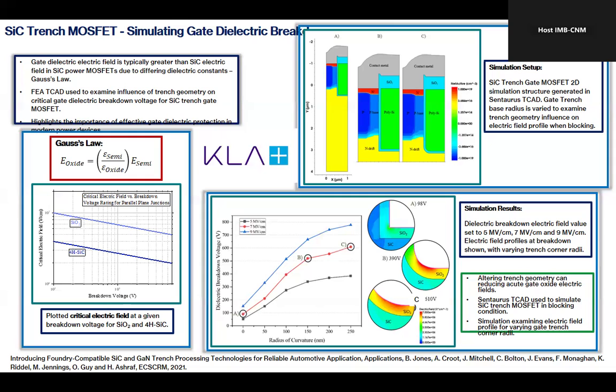But for this study, we didn't do that. For us, it's more of an academic study, because we're interested in trench technology. We really wanted to understand how rounding the corner of the trench etch in a power MOSFET can relax that field. How much can we relax it? You never know. You might not need additional structures if we can have a thick bottom oxide and a high radius of curvature at the trench. You might not need the additional features around that. You could simplify the device process.